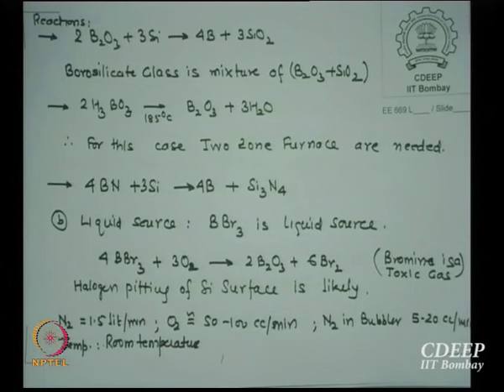There is also a possibility of making a solar cell with cheaper sources, which are called boron nitride sources. There are wafers of boron nitride. You put a silicon wafer in touch with boron nitride, on both sides silicon, so both sides are the same. The polished surfaces of silicon touch a boron nitride wafer in a slot, and the slot is adjusted so all 3 wafers are tight against each other. Such a number of wafers: 2 silicon, 1 boron nitride, 2 silicon, 1 boron nitride. That is heated, and boron nitride reacts with silicon into boron and silicon nitride. Instead of SiO2, now silicon nitride is the upper layer, which is also a mask for impurities. Of course, not as good a mask as SiO2, but it's still a mask.